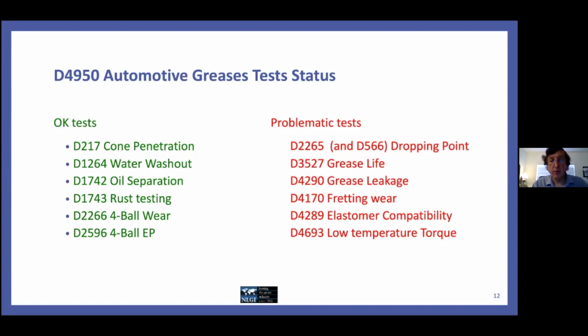The elastomer compatibility, which kicked off this original discussion: the D4950 does not control the elastomer used, and it belongs to the SAE Aerospace Materials Group, and they had made changes and not informed anybody, and when people went to buy the elastomer, they found it was not available. And so the big concern there is availability of the elastomers, a lack of control of the elastomers, and the other feature was, because they're aerospace materials, were they relevant to the type of seal materials used today? The other final test was the low temperature torque. This is again a wheel bearing test method, and so is that the right test method moving forward? And also it's at -40, which is typically much too cold for normal applications.